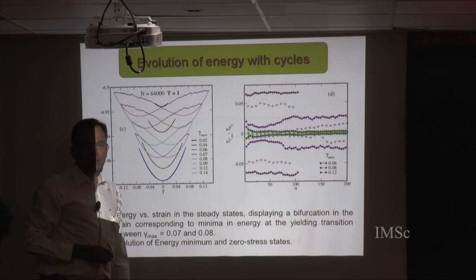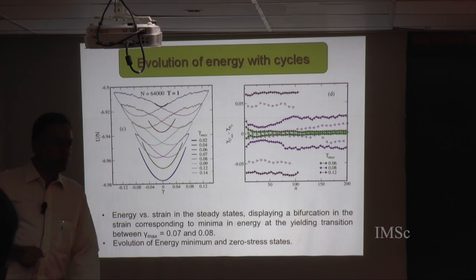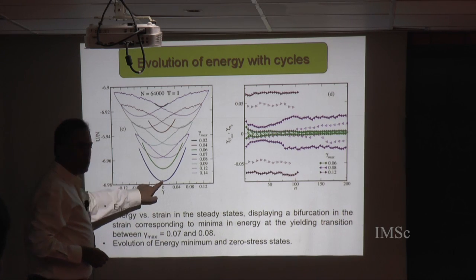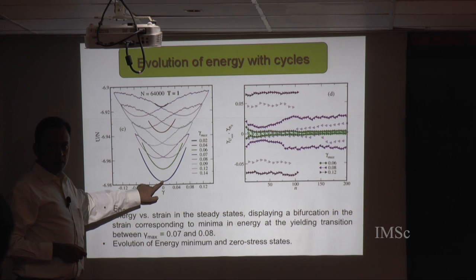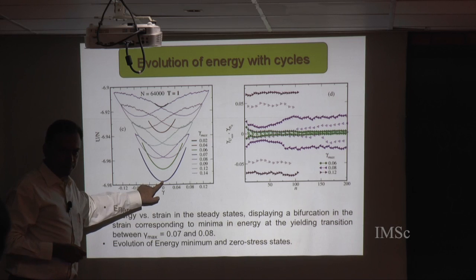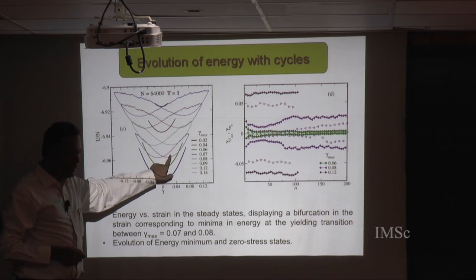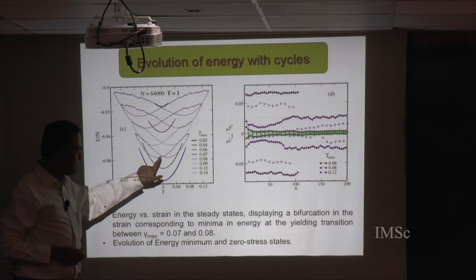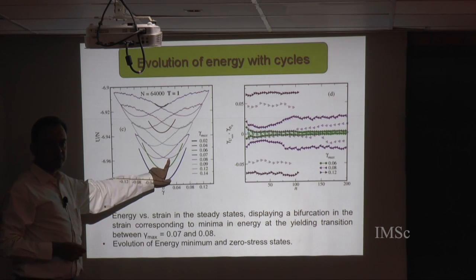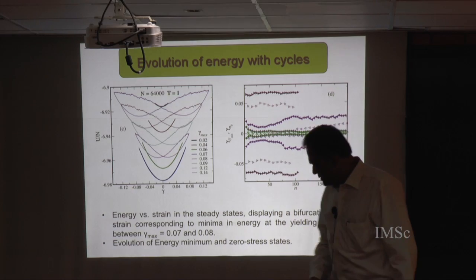No, my question was that up to the blue curve, right - up to that stage, the behavior would be fully reversible. If you do a loading and unloading, then beyond that, it's not reversible. There is a residual strain at which you get the minimum. Correct, that's right. Hysteresis, you are getting above that, right? Yes, absolutely, correct.